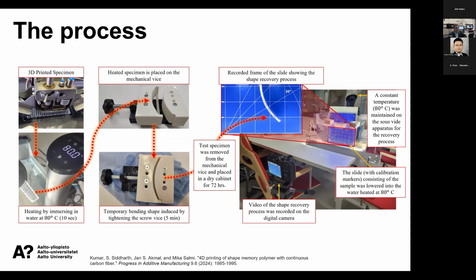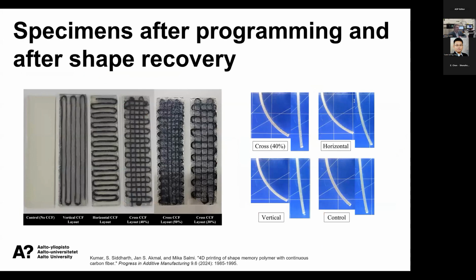We used a digital camera and camera monitoring with some software to get detailed answers on how these different fibers would influence it. So here are the specimens. We have a control specimen with no carbon fiber, vertical carbon fiber specimens, horizontal, cross with the layout 40, cross with the layout 50, and cross with the layout 30. So different kinds of infills, and of course we could use different fill-outs, but this was the first to try.